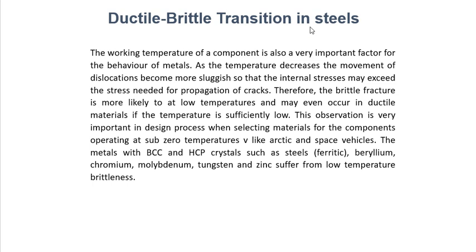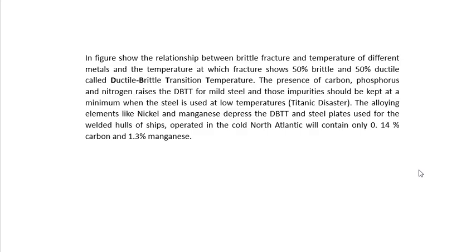That is the most important part of knowing this type of behavior. The figure shows the relationship between brittle fracture and temperature of different metals, and the temperature at which fracture shows 50% brittle and 50% ductile is called the ductile brittle transition temperature, DBTT. The presence of carbon, phosphorus and nitrogen raises the DBTT for mild steel, and those impurities should be kept at a minimum when the steel is used at low temperatures, right? Like the Titanic disaster.